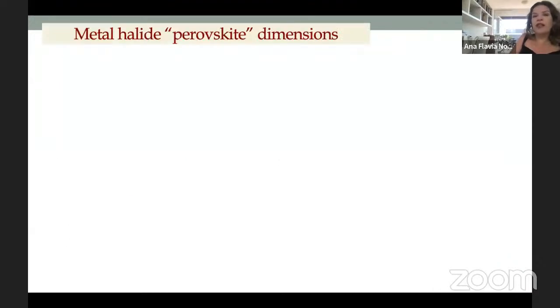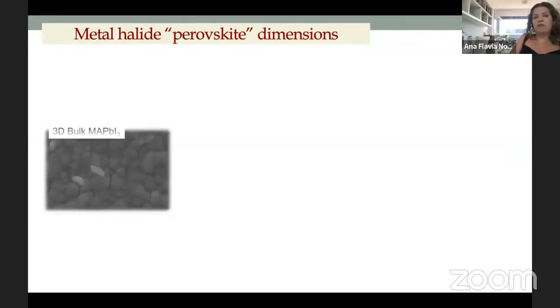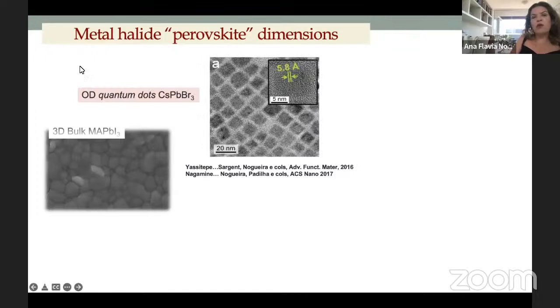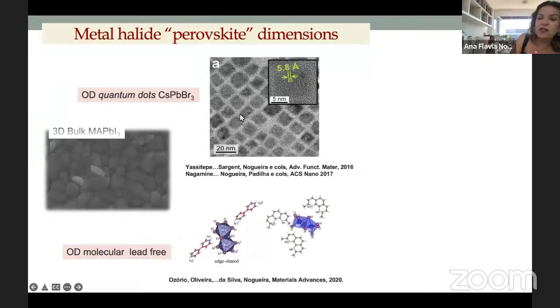So you can also make these perovskite materials in different dimensions. This is the most known structure for PV applications. This is the bulk MAPI. This is just a standard SEM image. But you can also have quantum dots of perovskites. In this case, the most studied composition is cesium lead bromide. You can see very nice images of these quantum dots for light emitting applications.